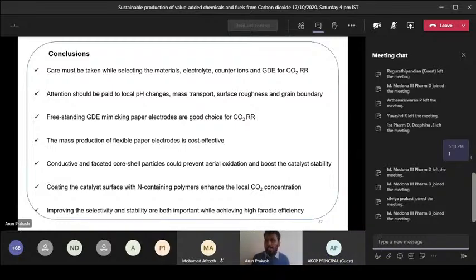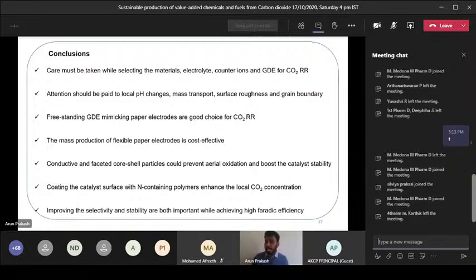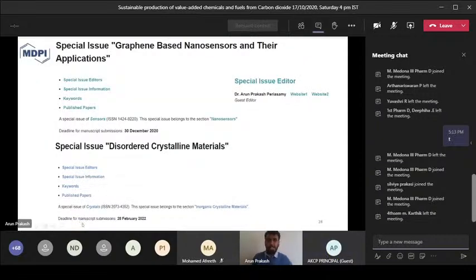These all can tune your activity and oxidation. How much it can oxidize you can also control, and you can control the stability and catalytic activity. Coating the catalyst surface with nitrogen containing polymers is very important because it increases the local CO2 concentration. Improving the selectivity and stability are very important for increasing the Faraday efficiency.